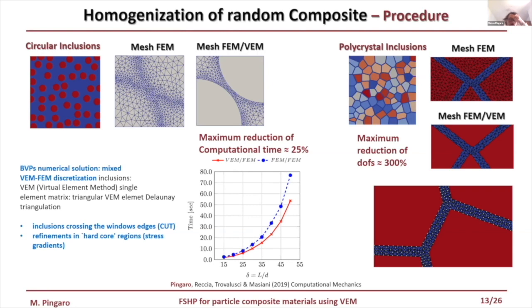The maximum reduction of the computational time is more or less 25%, and apparently this is a low value. But when we perform hundreds of analyses, the reduction in the procedure time is very consistent. While in the case of polycrystalline material, the reduction in terms of degrees of freedom is about 300%. It is a very high value.